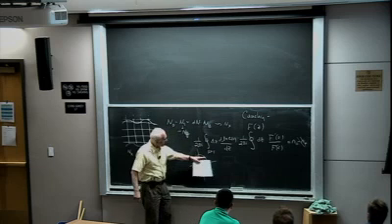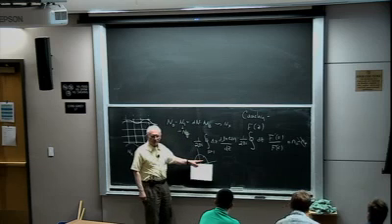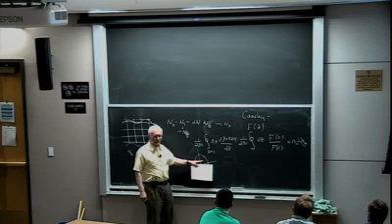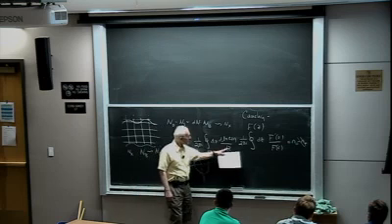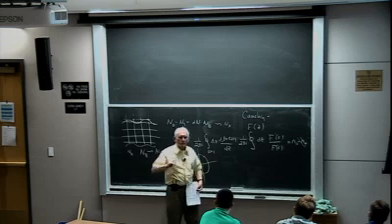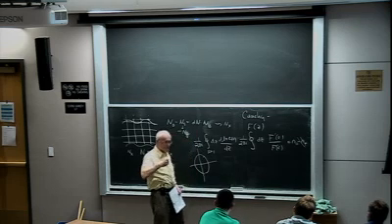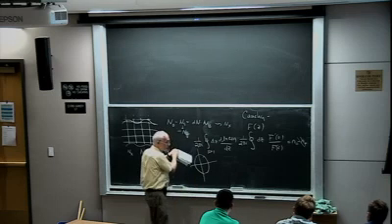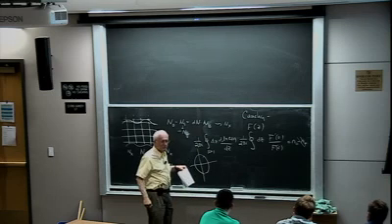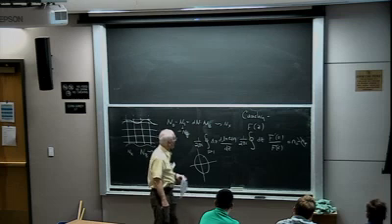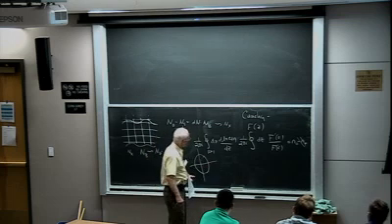If I have a zero that lies within the unit circle, its magnitude is automatically less than 1, and therefore I've counted for you the number of possible modes that will penetrate from the left to the right into the system.